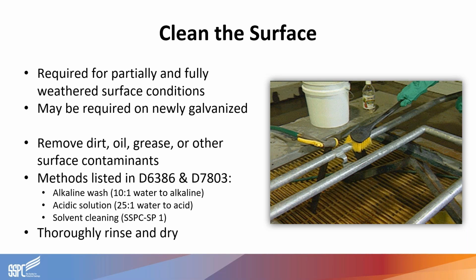But especially where acidic and alkaline cleaners have been used, you want to avoid letting that sit on the material and attack the coating during cleaning. You want to be quick with it. So it's strongly recommended to heed those suggestions in the standard that mention that time period, but also to rinse that material thoroughly, preferably multiple times. Anytime this is left unhighlighted or unspecified, and a paint applicator may not be familiar with galvanizing, they may not feel the need to heed those recommendations. And so highlighting this concern can aid in preparing duplex systems.